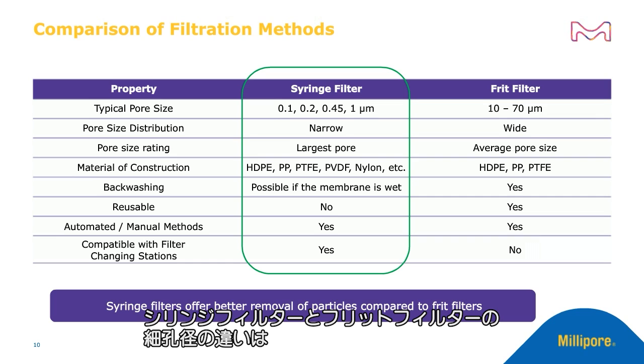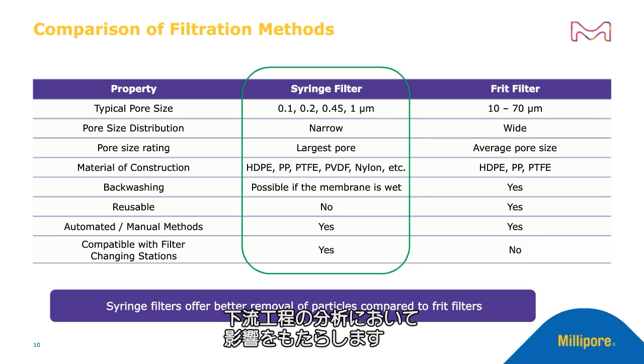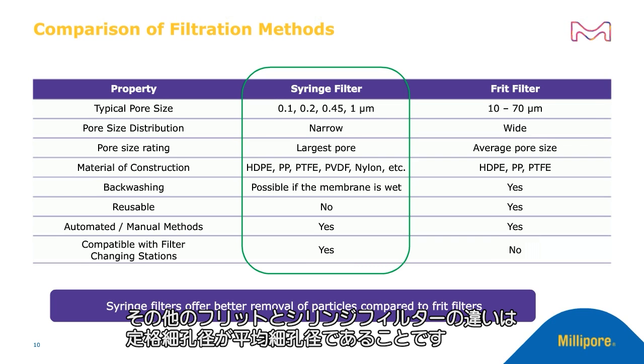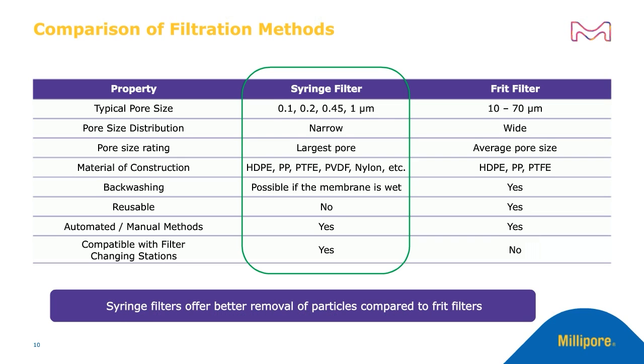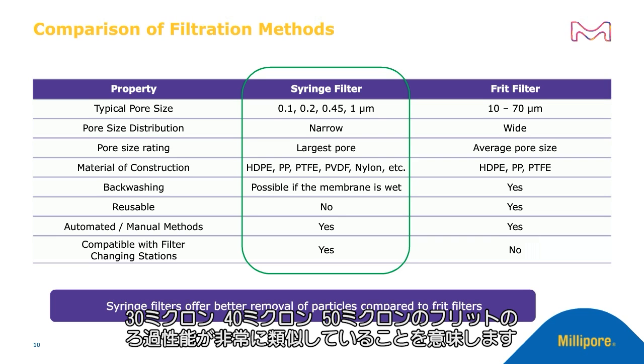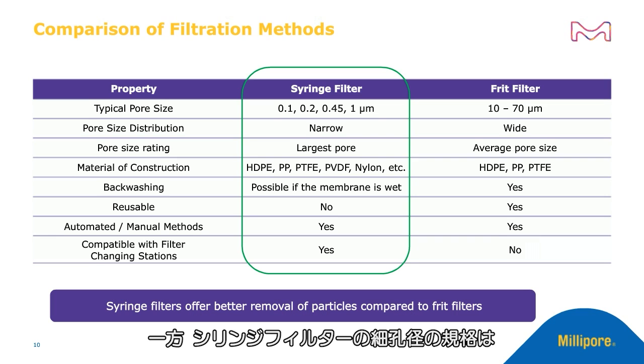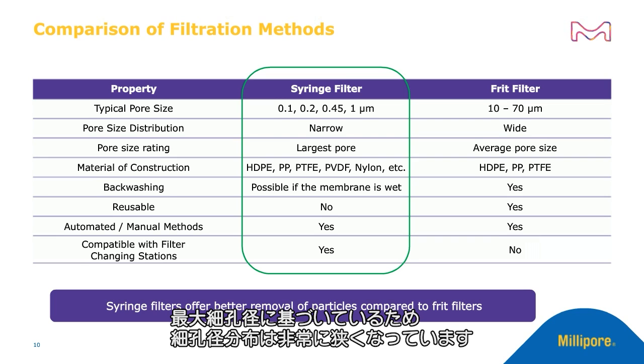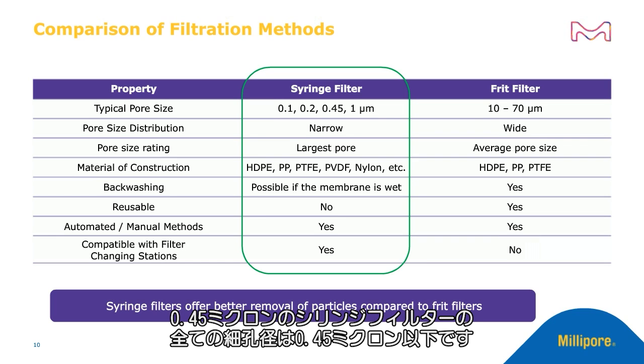So the typical pore size difference between syringe filters and frit filters can be substantial when it comes to downstream analysis. Another important difference between frits and syringe filters is that their pore size rating is an average pore size, which implies that the filtration performance of a 30 or a 40 or a 50 micron frit can be very similar. On the other hand, the pore size distribution for a syringe filter is very narrow because the pore size rating for a syringe filter is provided by the highest pore size. And what that means is a 0.45 micron syringe filter will have all the pores smaller than or equal to 0.45 micron.